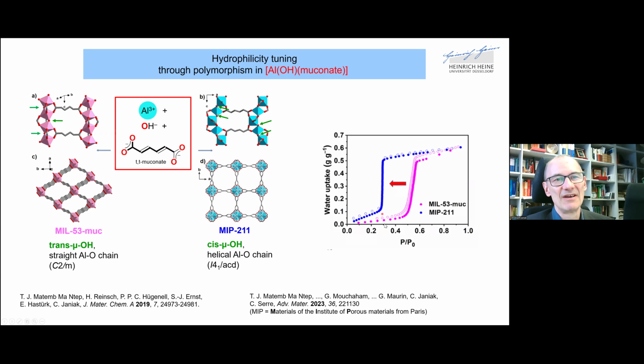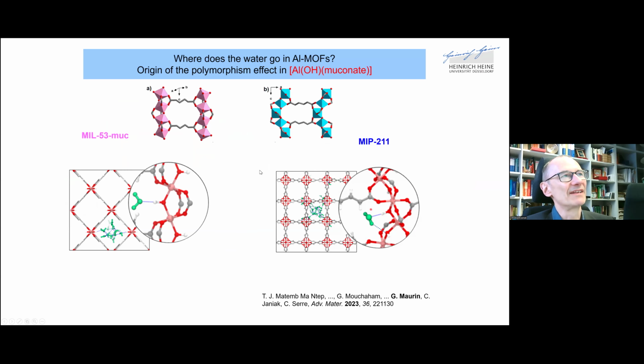Its water uptake occurs around 0.3 relative pressure. Now, such a small change, you may wonder, and such a drastic effect. It was with the help of a theoretical chemist that we could understand why that happened, or how this change in water uptake came about. So the water, when it binds or absorbs in the MOF, has to find some points of higher hydrophilicity.